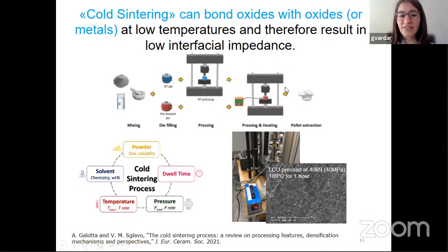Basically, cold sintering is a very simple method, and that's what we are doing in our lab here as well. You are taking a material, you are mixing it with a solvent, and then you are heating it and pressing it at the same time, which is what you're doing here. And there are a lot of parameters that you can control in order to make these interfaces better or more compatible with each other. But the idea is that solidifying ceramics at these really low temperatures, like 180 degrees, is very advantageous because we know that high temperatures degrade these interfaces.